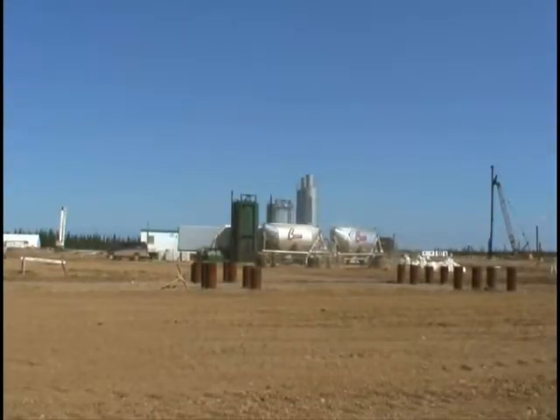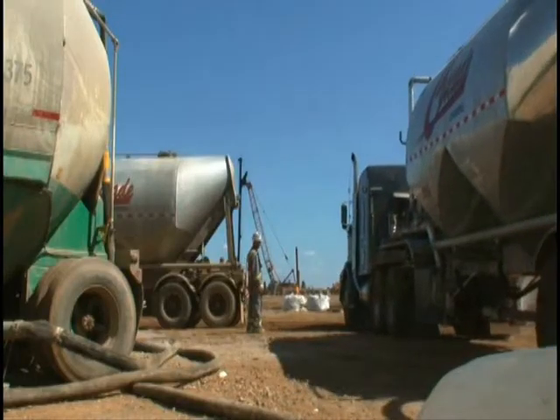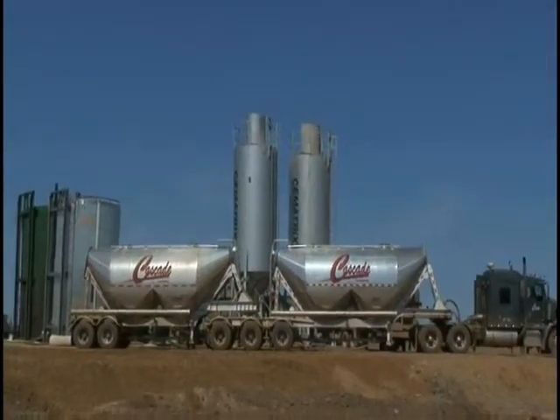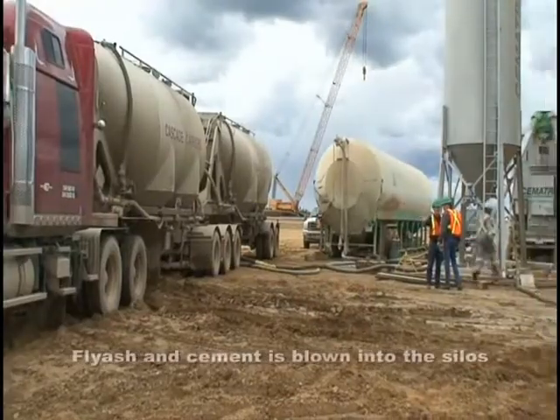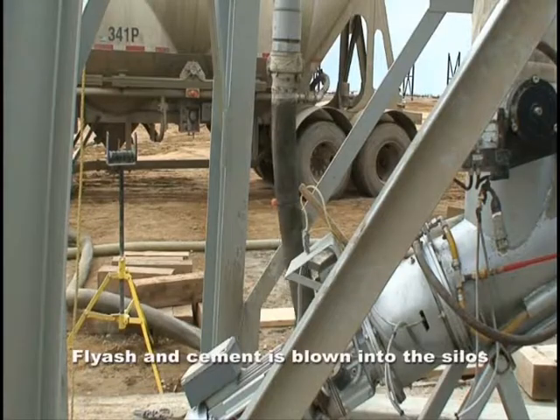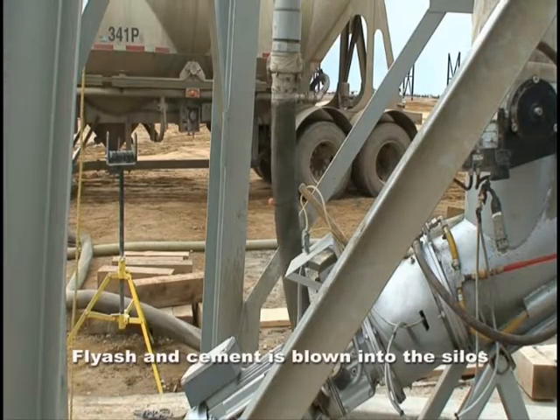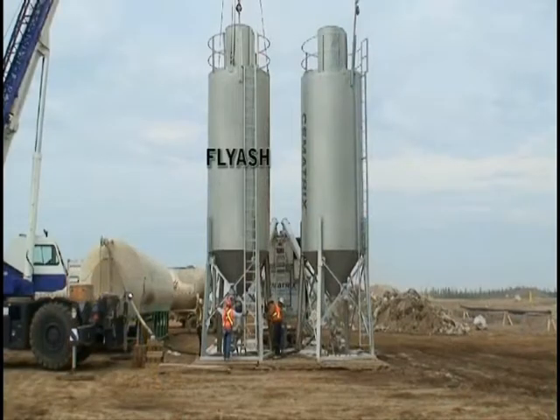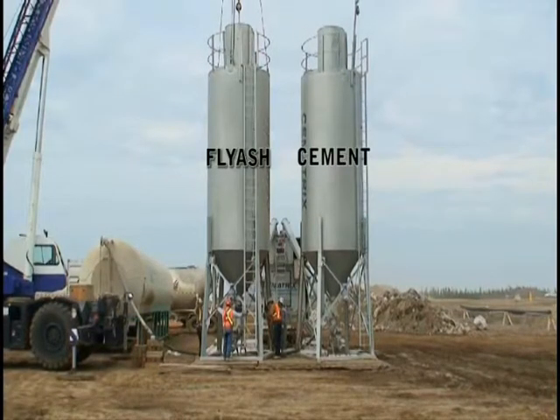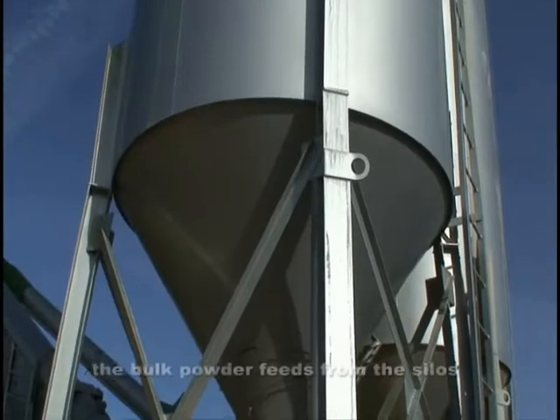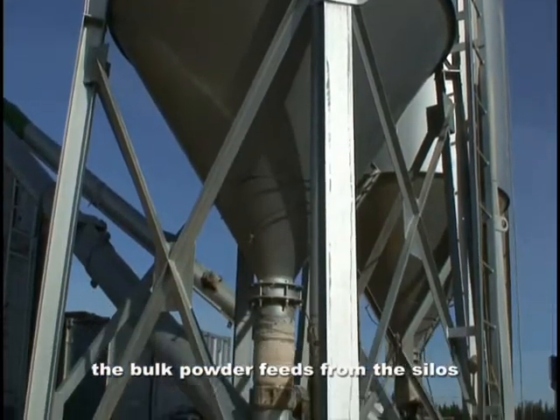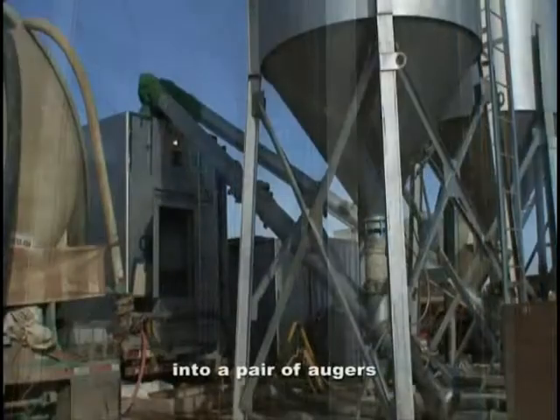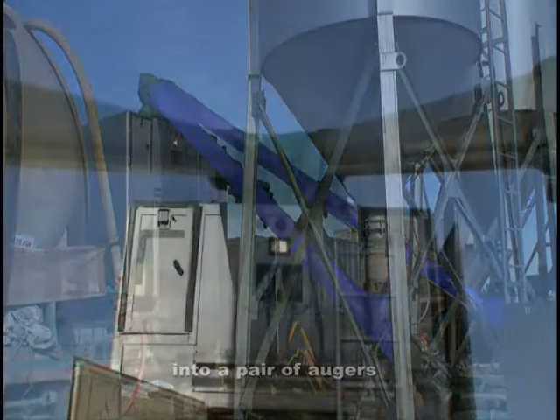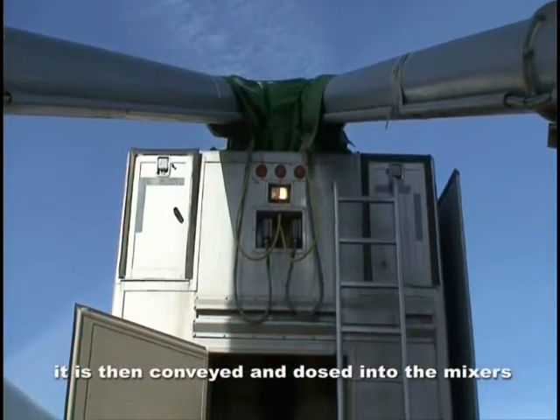Bulk cement is delivered to site and blown into the portabulker, which holds up to 4 full truckloads. Cement is then transferred into one of the two silos. Bulk fly ash is delivered and blown into the other silo. The bulk powder feeds from each silo into the augers and is conveyed by a fully automated computerized system into the batch mixing plant. It is dosed into one of the plant's twin mixing pods, where it is mixed with water and blended with high-speed impellers.